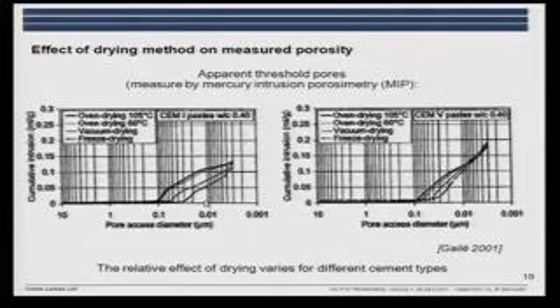And what you also see is that depending on the material, here we have a CEM I, and here we have a CEM V. It's two different types of cement. The method of drying has a different relative impact on the measured porosity. So this is something we need to consider, and first of all, you need to do it in a repeatable way when you're comparing, but you also need to consider how to do it to get results which you can use.